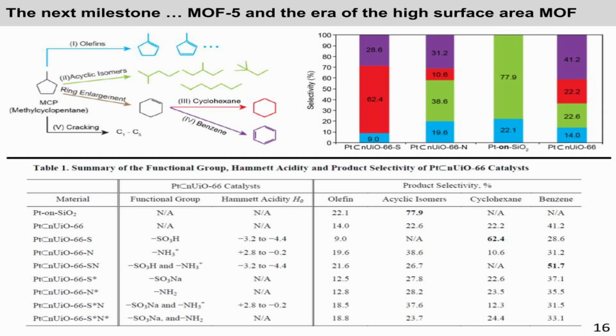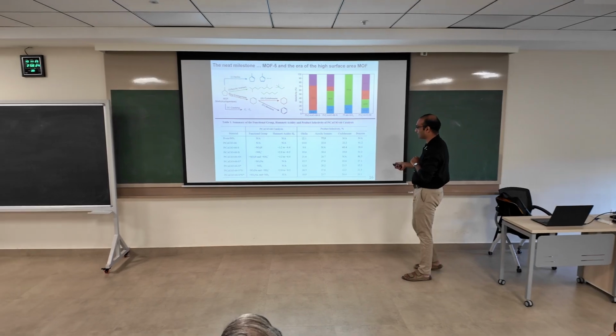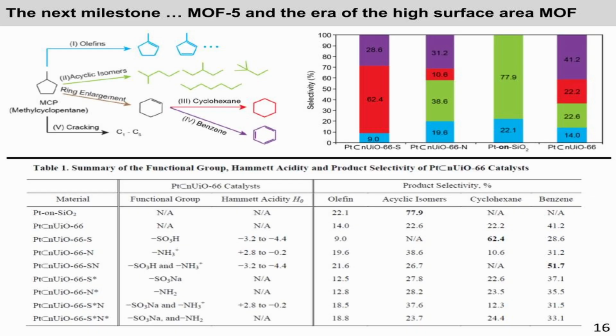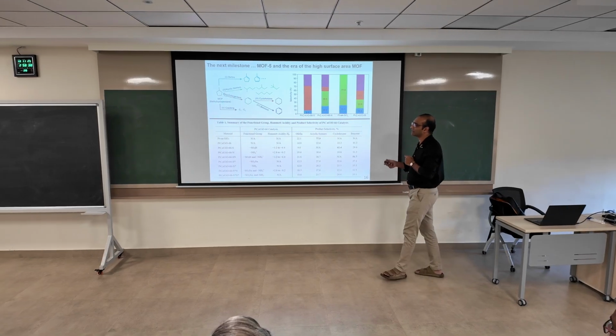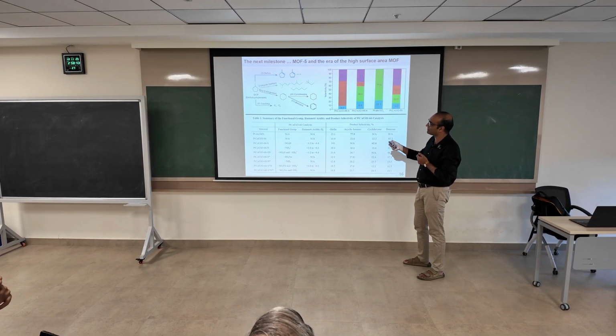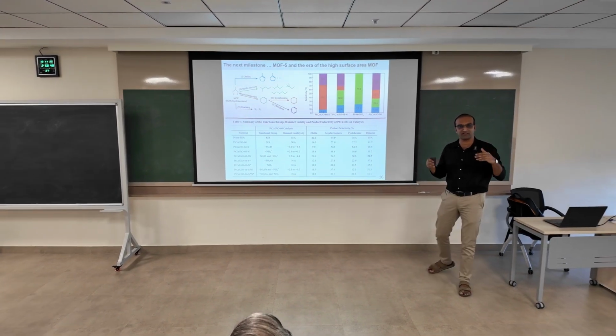Like these things. Okay. But whereas when you do these UiO, when you put the platinum nanoparticle inside the MOF, you can selectively control it to give you either cyclohexane or benzene. Okay. And they try to increase it. Like even in this particular case, they had an SN linkage. They got more benzene than they got cyclohexane. So you can tune the nature of the product that forms when you're starting with methylcyclopentane. Yeah, methylcyclopentane. Okay. Starting with this, you can crack it to get different products. Okay. These are not valuable, but all of these are valuable. The problem with platinum is you cannot control what fraction it is. It will usually break it up into any number of things. It can even give you gas, like methane, and that's completely useless to us.